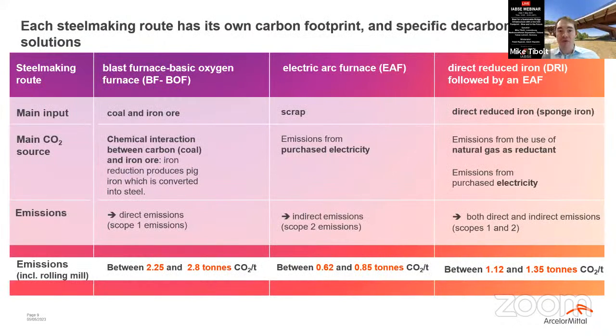Therefore, let's first of all have a look at each steelmaking route commonly used to produce steel, and what the carbon footprint of each of these production routes is. Starting with the blast furnace route, where the main inputs are coal and iron ore, and the main source of CO2 comes from the chemical interaction between the coal and the iron ore during the reduction process. The emissions are direct emissions coming directly from the steel production. The emissions lie between 2.25 and 2.8 tons of CO2 per ton of steel produced, including the rolling of the product.